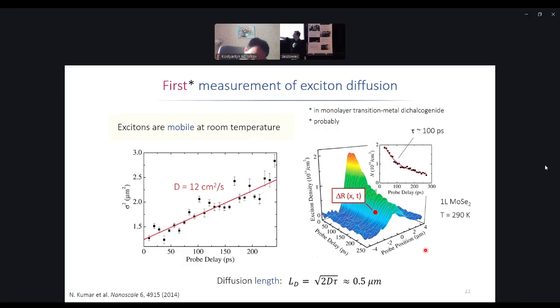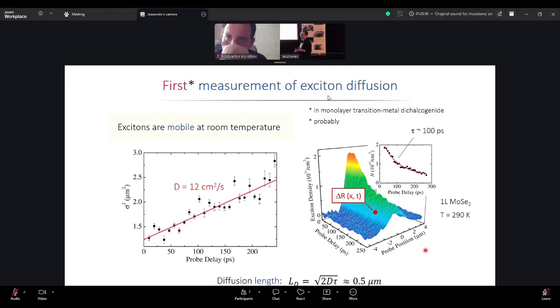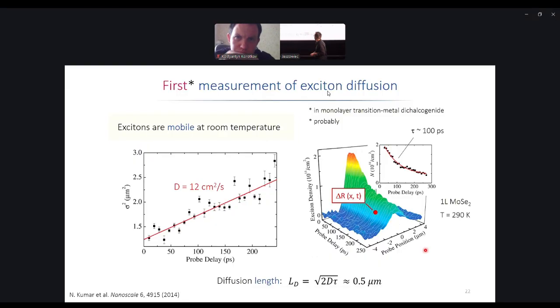Quite an important parameter, and sometimes this is the one that can be measured, and I will show you an example, is the diffusion length. It's defined as diffusivity times tau, sometimes there is a 2. That more or less tells you on average during the lifetime of the exciton how far they travel. Yeah? And in some materials this can be as short as tens of nanometers. In some materials it can be as long as many micrometers, or in some cases even millimeters.